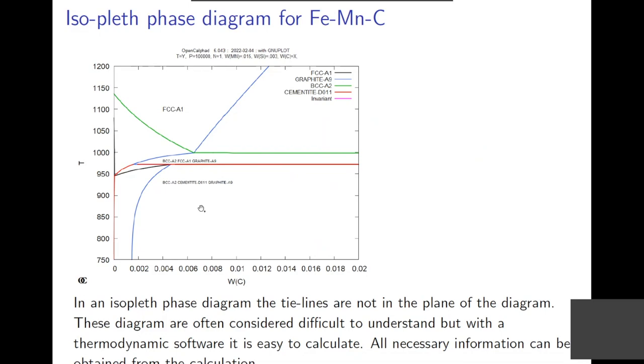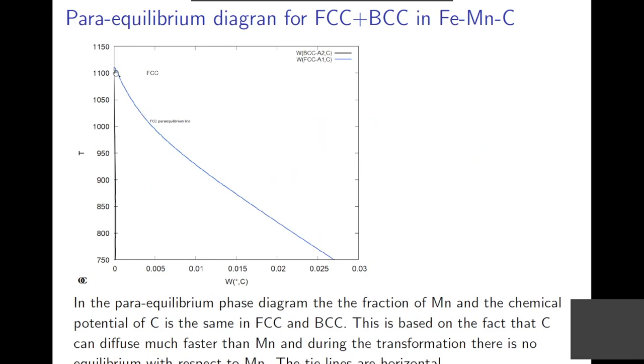And as Hari Bhadeshia showed, we can have lots of other transformations than the equilibrium ones. And one of these types is called the para-equilibrium diagram. In the para-equilibrium diagram, you assume that the manganese does not redistribute between the FCC and BCC. So that when you cool down the FCC, your BCC phase here will inherit the same manganese content as you had in the original FCC phase, but you will have the same chemical potential of carbon. And that gives you a diagram like this. At present you don't see the difference, but here you have tie lines. It's basically a binary system, assuming that manganese behaves like iron.